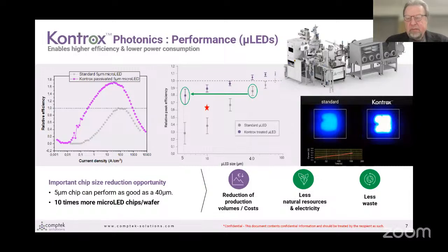And finally, you can see the picture of the new tool here on the right corner. The performance of micro LEDs is a very typical example of Kontrox's role in passivation, because you can see that we can contribute to chip size reduction. For example, a 5 micrometer chip can perform as good as a 40 micrometer chip if it is Kontrox passivated. This example, by the way, is a 5 micrometer blue gallium nitride micro LED. And you can also see in the picture how different the brightness level is between a standard one without Kontrox passivation and the Kontrox passivated LED.